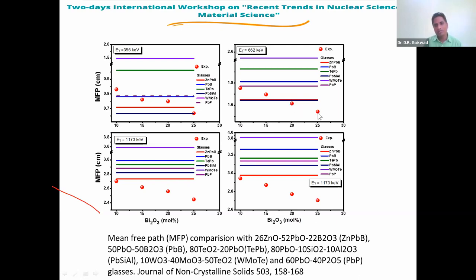Here again, you see these glasses have a low mean free path at chemical compositions of 20 and 25 mole percent of bismuth. Again, if you see at bismuth composition of 10 to 15 mole percent, then the mean free path is comparable to the other aluminum lead silicate glasses or other heavy metal glasses.